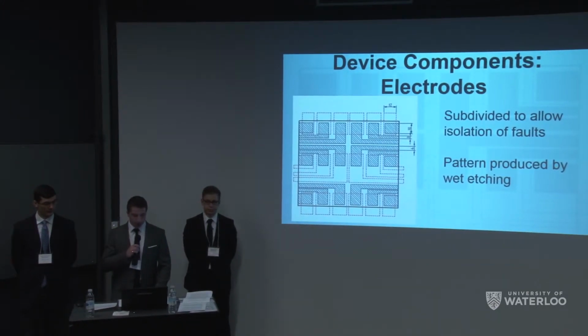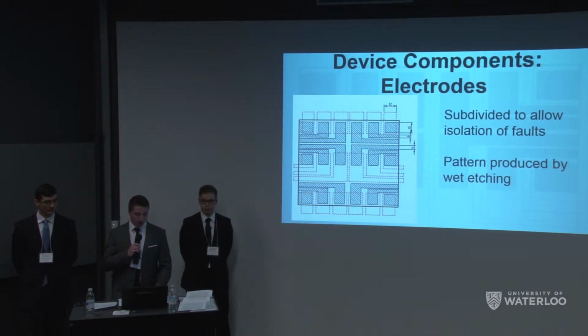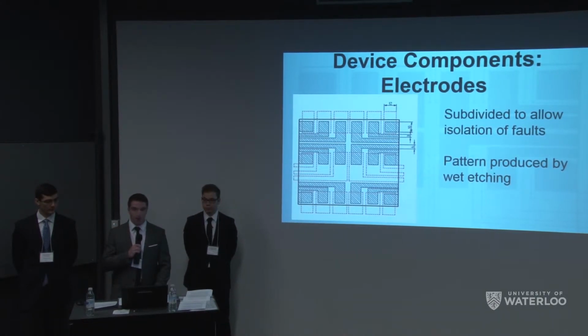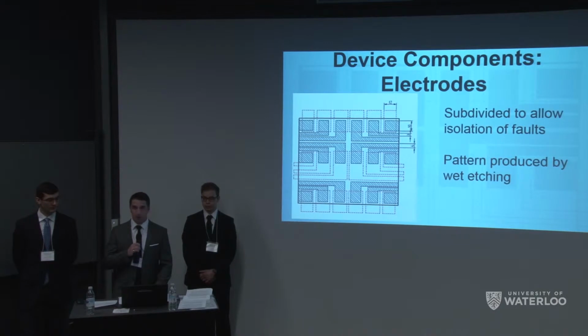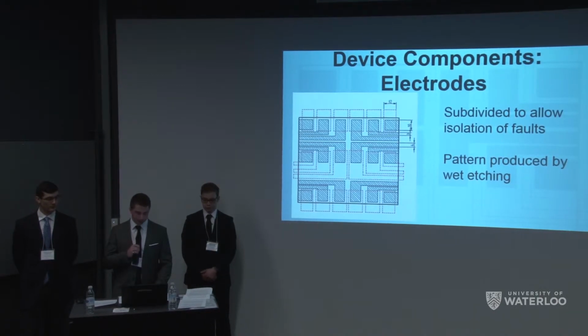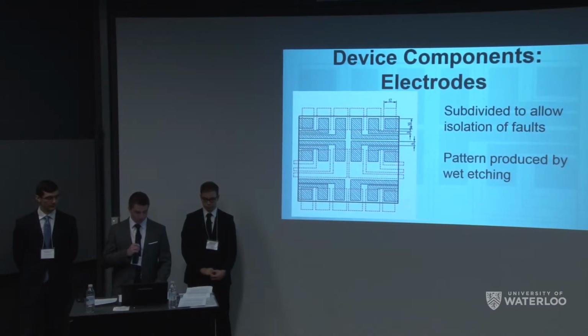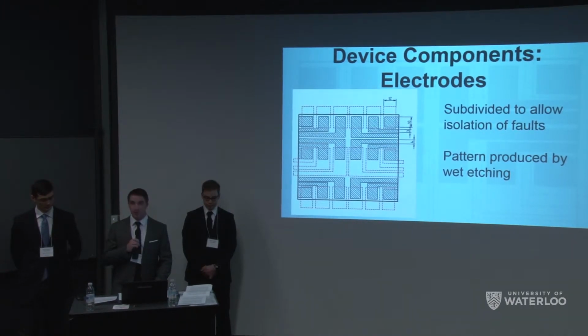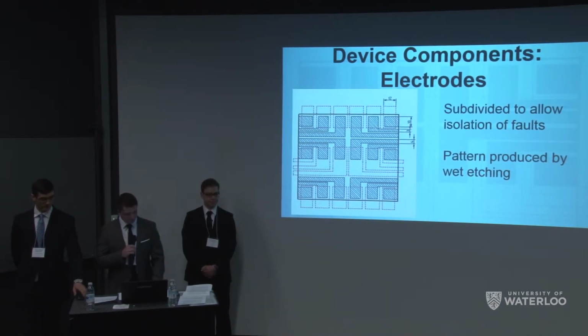So for this project, we created a way to etch ITO patterns using the same photoresist found in the circuit board industry and without using hydrofluoric acid as a wet etch solution, which is quite a safety hazard. This method is cheap, safe, and reproducible. The silver nanowires were patterned using a stencil, which is also cheap, easy, and has a high throughput.